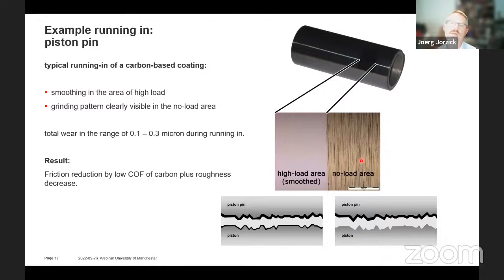And we were, of course, interested in understanding how much of the coating is used up for this kind of running in. And if we think typical coating thickness are around 2.5 micron total coating thickness. So what we did is we measured the coating thickness along this line, and we found that there was a difference from this area to this from 0.1 to 0.3 micron. So that means for this running in behavior, approximately 10% of the total coating thickness was used up.